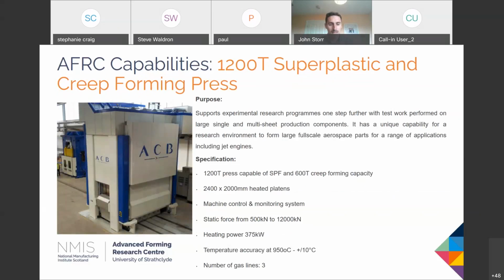We have then our 1,200 ton superplastic forming press, and this also has a quite unique capability of creep forming. So along with the 1,200 ton SPF capability, it also has 600 ton of creep forming capability. So not only using the gas pressure to form components, but we can also just use the tonnage within the press to creep form thicker sheet components. And we've done that with some thicker sheet titanium components in the past as well.